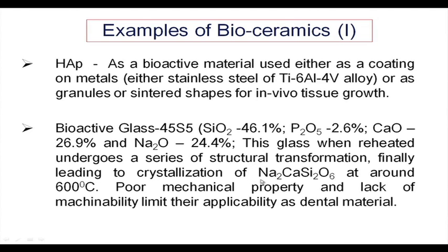This is leading to crystallization, because glass is a thermodynamically unstable material which undergoes crystallization when heated, and these ceramic nanocrystals come up at around 600 degree centigrade. So, the poor mechanical property and lack of machinability limit their applicability as dental material. Although there are other materials which can be used as a dental replacement or dental implant, this is one of the first bioactive glasses which was developed quite some time back, and it is being used extensively, but it has certain limitations. That is what has been mentioned here.